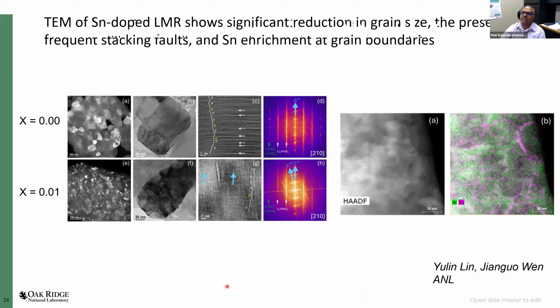So we also followed this up at TEM, and what we find is consistent with the X-ray diffraction. In the starting materials, the grains are fairly large, but the grains, I don't know how clear it is to see, break down into much smaller regions in these samples. And then if you look at the EDS spectra, what you find is that tin seems to have a propensity to go to these regions, which we believe are these grain boundary regions.